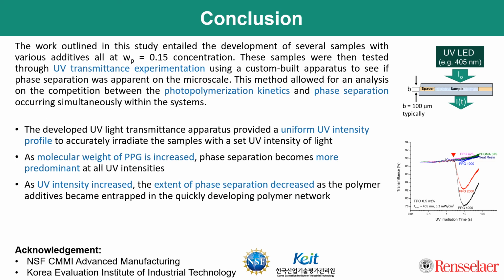So then to conclude, again, we made this neat resin comprised of a 3-to-1 mixture of PETA to 2-EHMA with 0.5 weight percent of TPO photoinitiator, and to that neat resin we added various polymer additives at various molecular weights at a weight percentage of 15% concentration. We also used a custom-built UV light transmittance apparatus, which provided a uniform UV intensity profile to irradiate our samples with UV light and essentially start our photopolymerization.